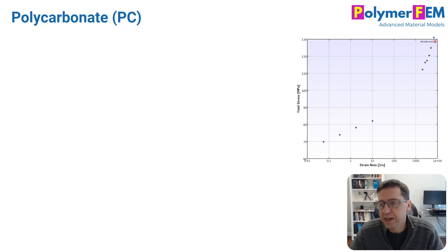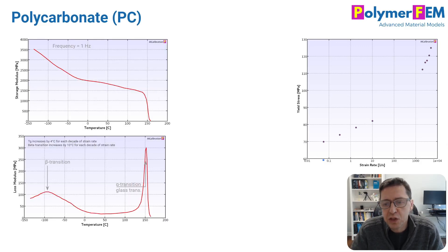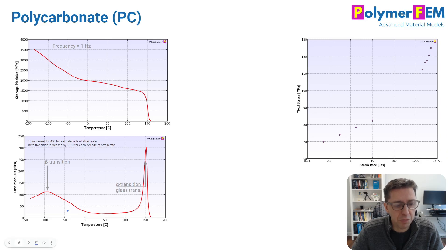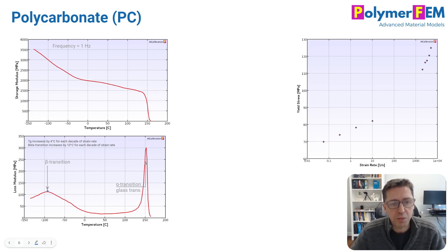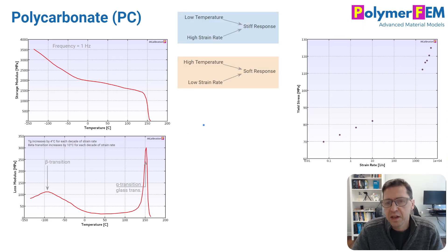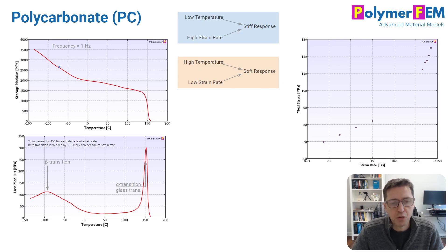Let's look at polycarbonate. If you plot yield stress versus strain rate for polycarbonate, you get a bilinear response. If you then take this polycarbonate and do a DMA temperature sweep — plotting storage modulus and loss modulus versus temperature — you see typical DMA traces. As temperature decreases, the storage modulus goes up. You see the glass transition temperature, called the alpha transition, and another peak in the loss modulus at lower temperatures called the beta transition.